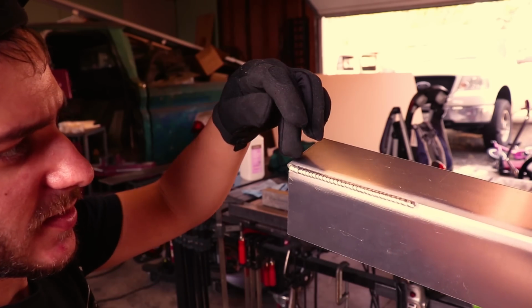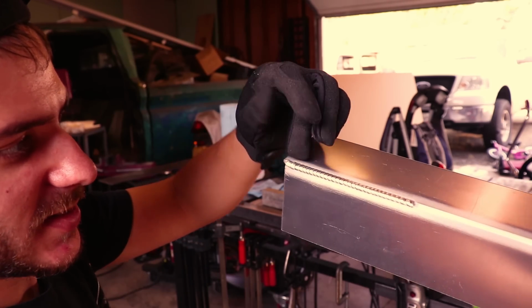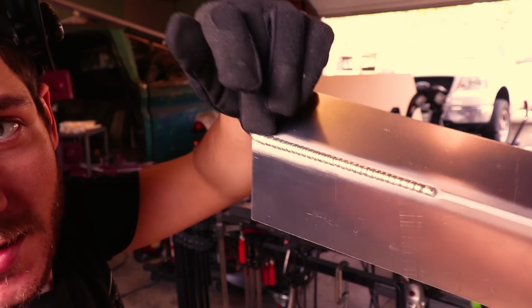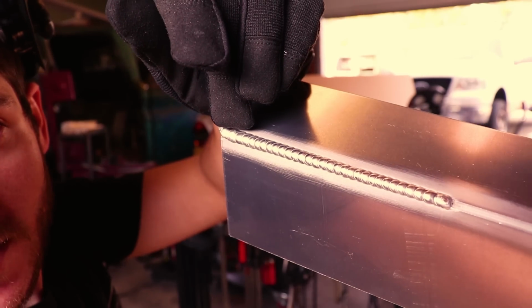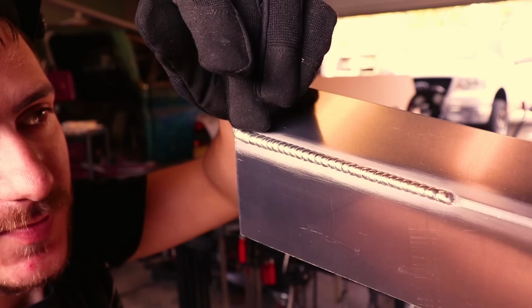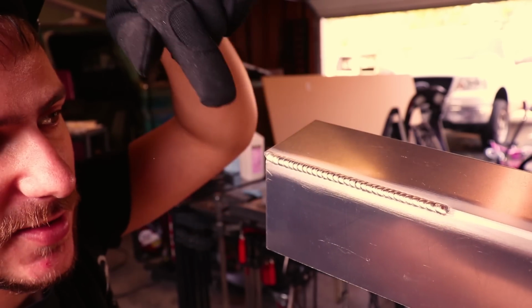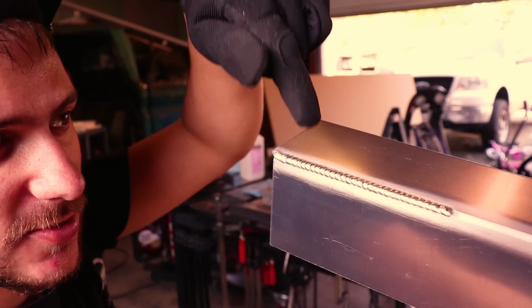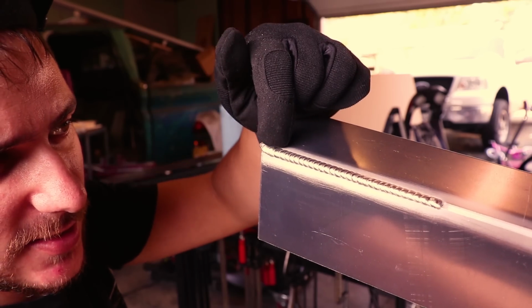So for this weld, basically all I'm doing is letting it puddle up and pool, and once it soaks in top, bottom, and you can see it in the crack. There's no horseshoe on it. Once it's in that crack,